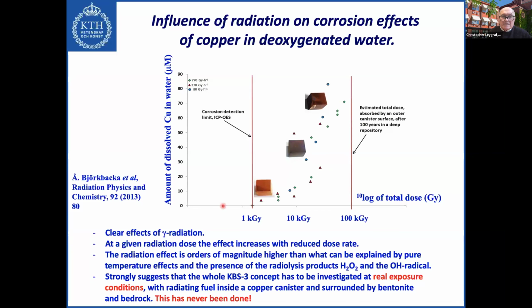And what you see here is the amount of dissolved copper in deoxygenated water as a function of dose of gamma radiation. Here's from 1 kilogray up to 100 kilogray, which corresponds roughly to the absorption after 100 years in a deep repository. So of course the radiation rate is higher than it is in natural conditions. But what it shows is that there is a very clear dose effect. At a given dose, the effect also increases with a reduced dose rate. So if you take any result here, let's say at a certain dose, you will see a tendency that the higher amount of dissolved copper, the more corroded copper, is shown at a lower dose rate.